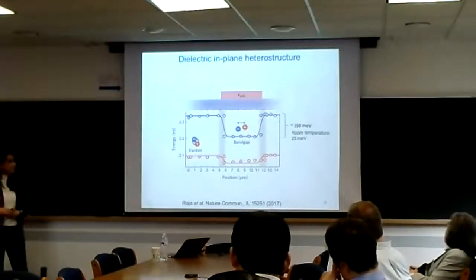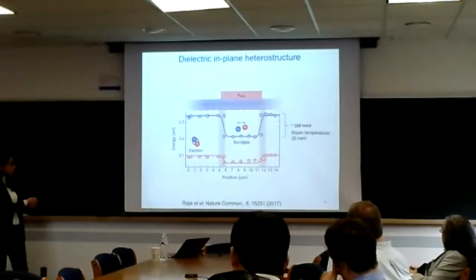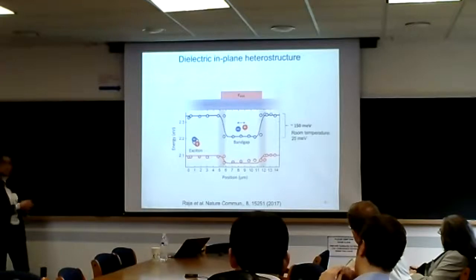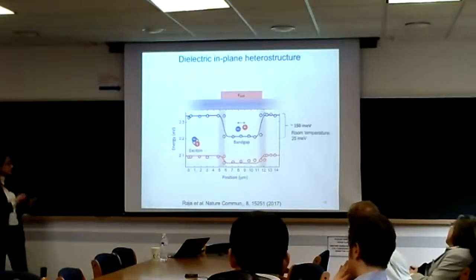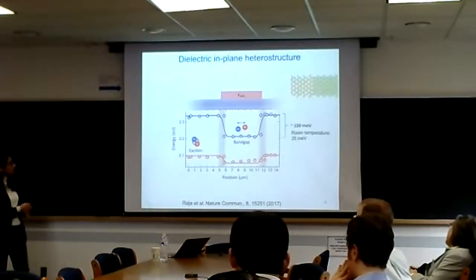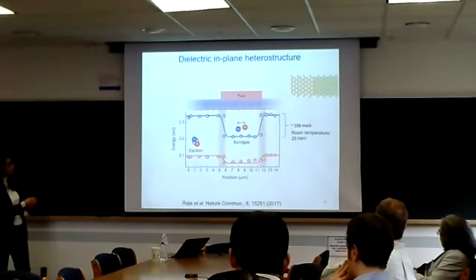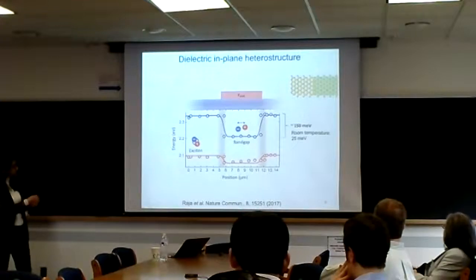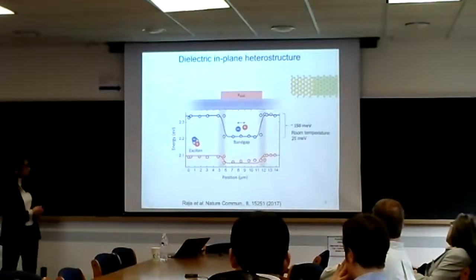So if you have a system like BN that has a binding energy of an eV, this effect will be even larger. The exciton does change as well, but it's a weaker effect because it's sensing less of the environment. And it's like having a junction between two materials. The only thing is right now we don't know how sharp the junction is because we're limited by far field optics here, our micron resolution.